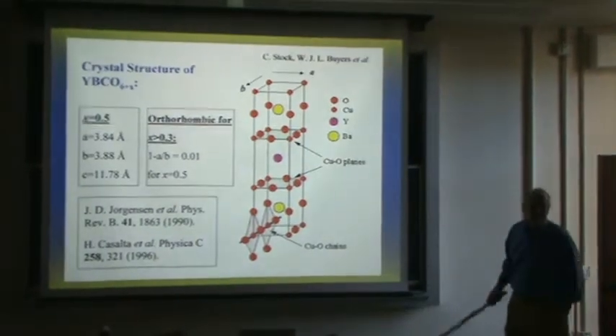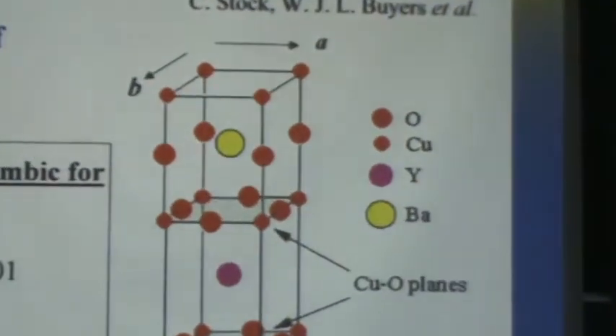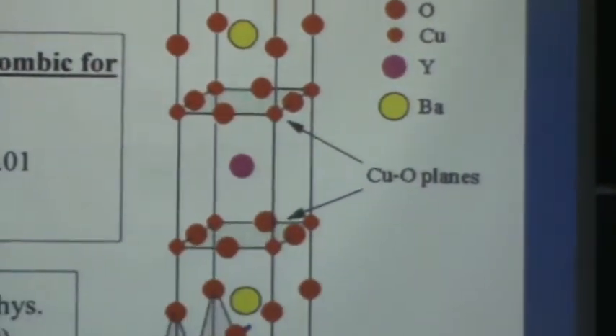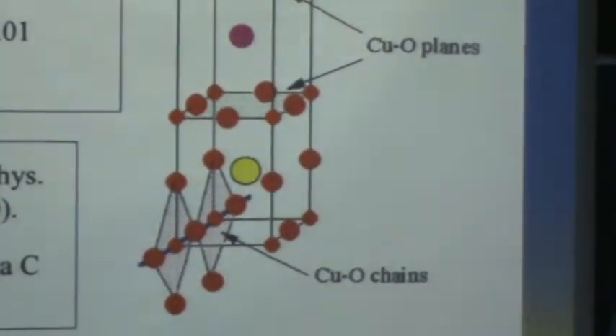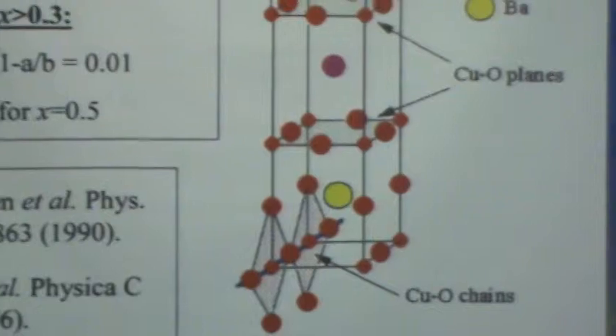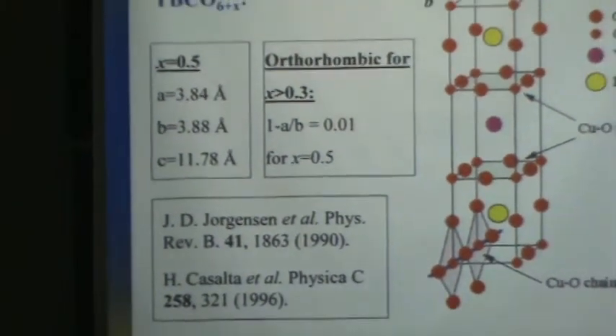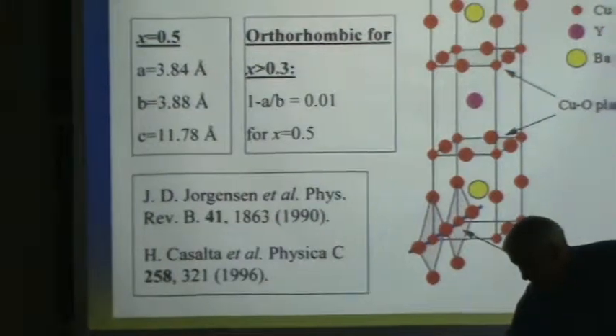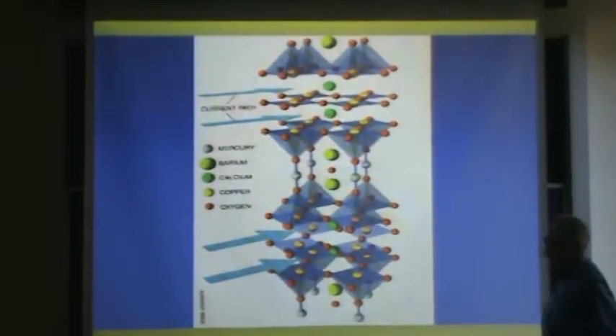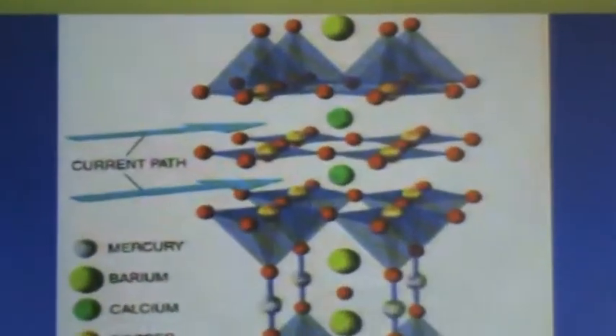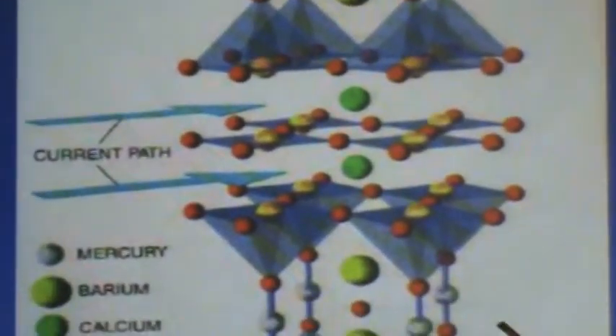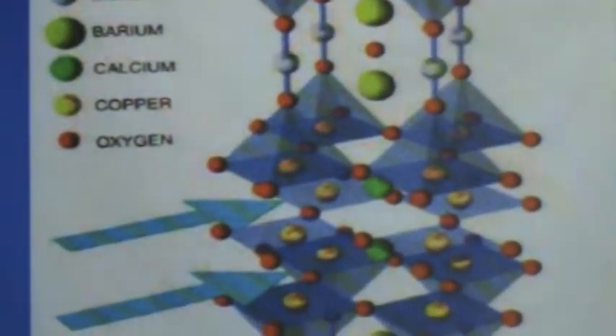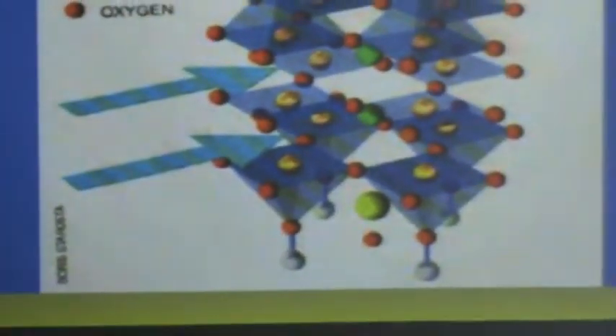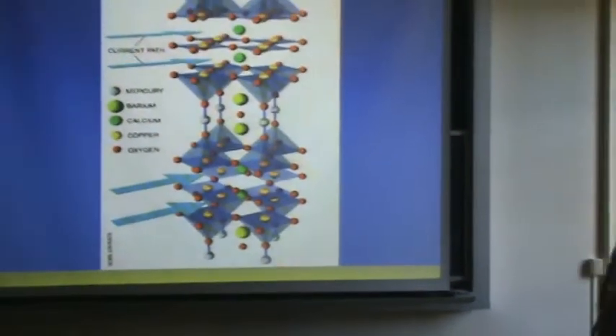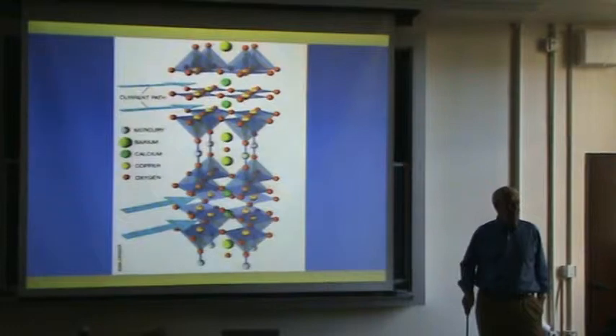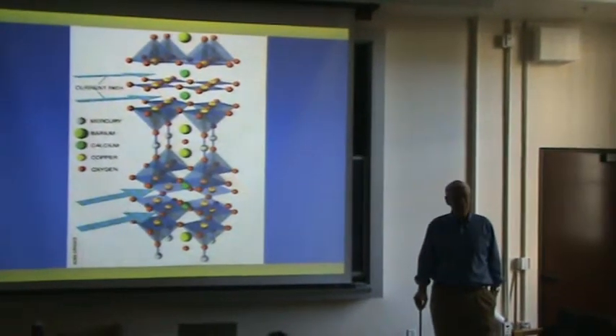The material that's superconducting above liquid nitrogen is called yttrium barium copper oxide. And rather than having sheets of copper oxide, it has a pair of sheets. They're still isolated from the others, so it's a bilayer material. But basically it's in essence the same. This is the material that sets the world record. This material is again based on layers of copper oxide, but in this case, mercury. You have mercury instead of lanthanum, and you put in a little barium and a little calcium and you squeeze it, and it's superconducting at 164 Kelvin, which is pretty remarkable.